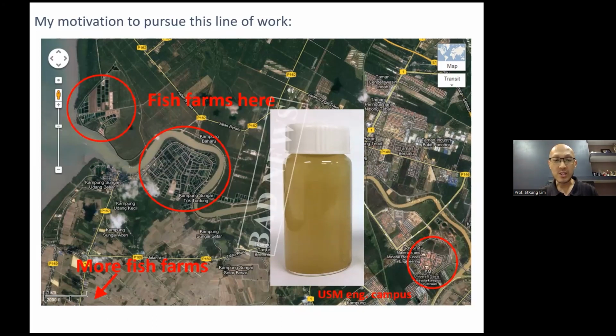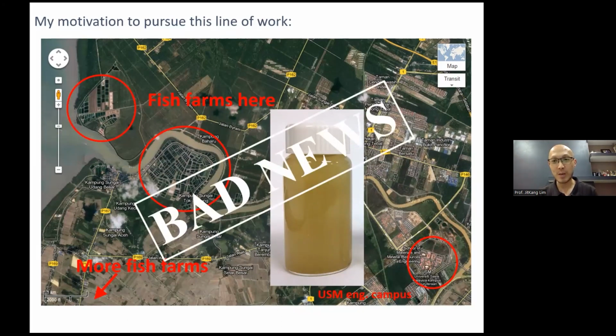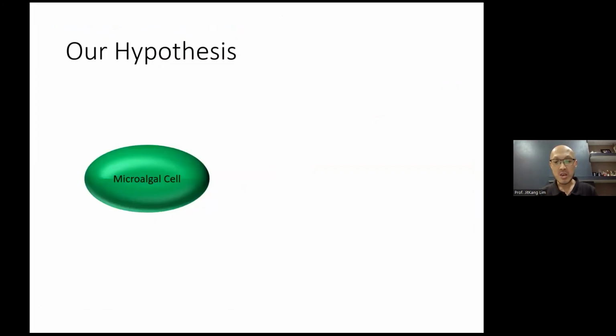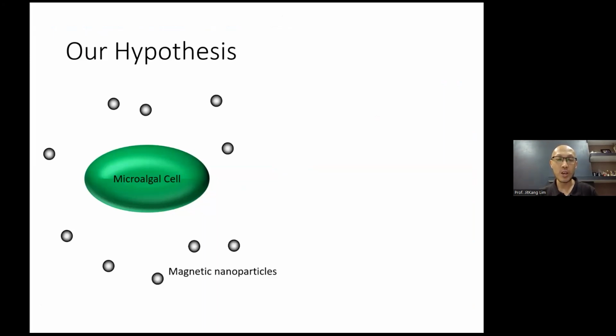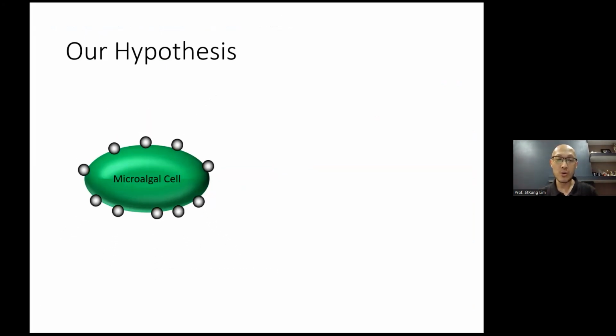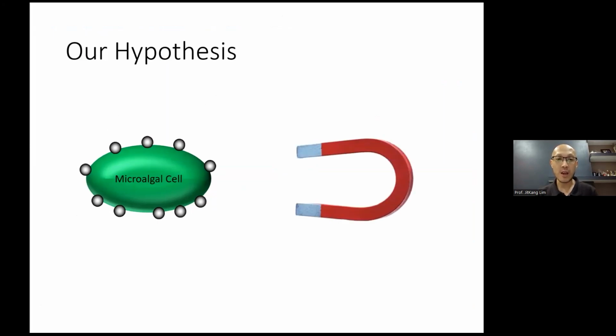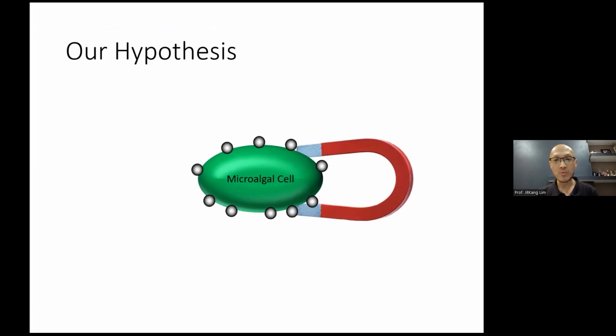Our take on this, of course, is that it's bad news for the local community, especially since our campus is so close to the fish farms. Our hypothesis is that even though the microalgae cell is a biological cell, most biological cells are non-magnetic. If we have a way to attach magnetic nanoparticles onto the microalgae cell, then all we need is to apply an external magnetic field to collect the microalgae cells out of the aqueous environment. So the whole idea is very straightforward. As long as we have a way to impart magnetic properties to the biological cell, we can separate them out by using a magnetic field.